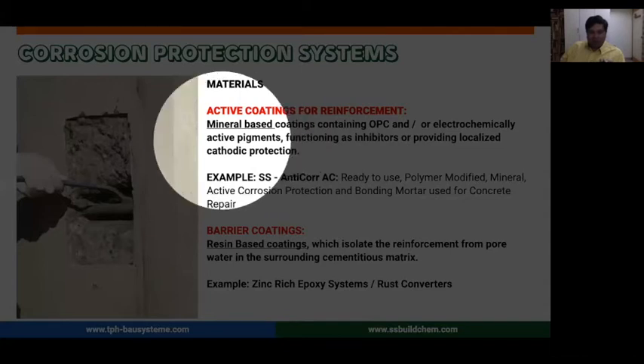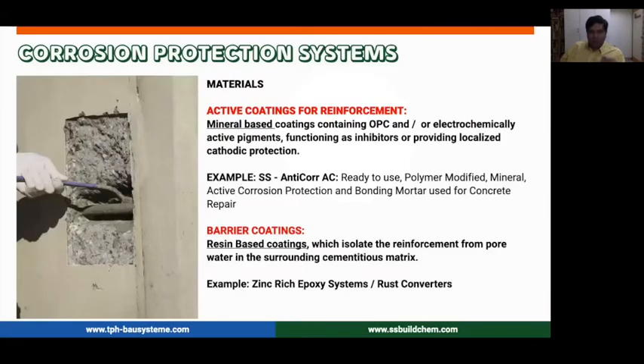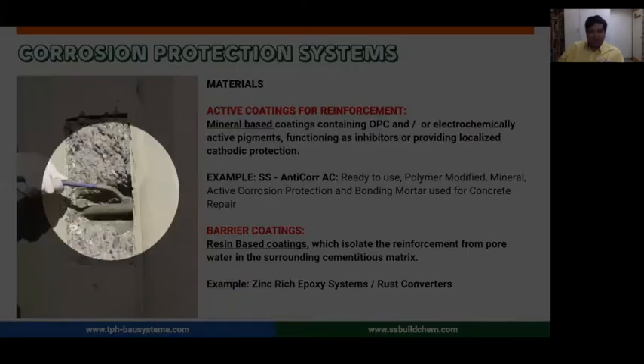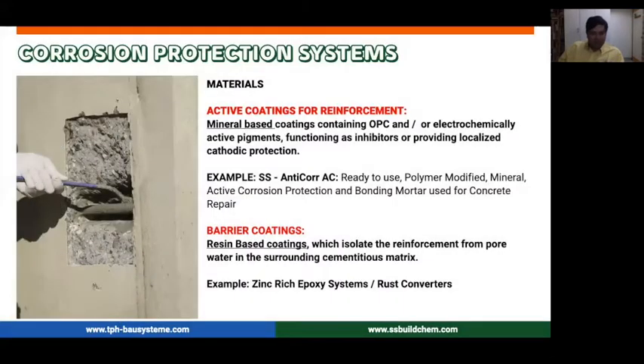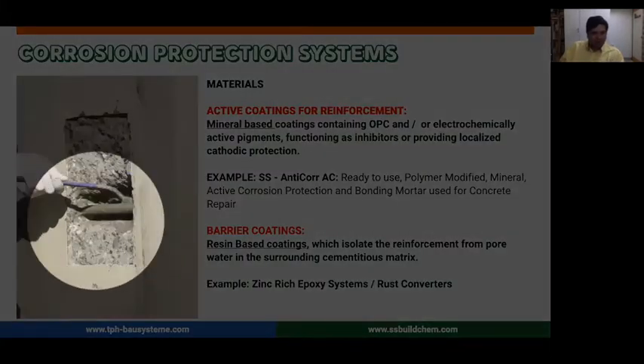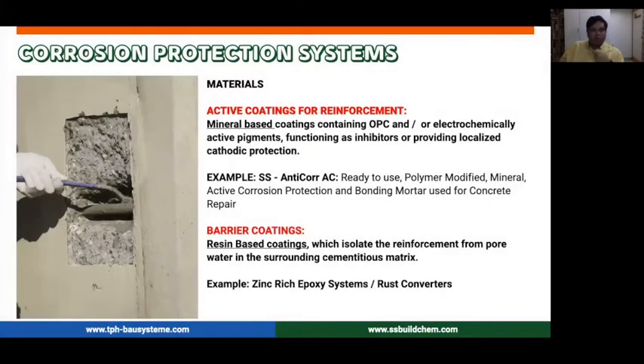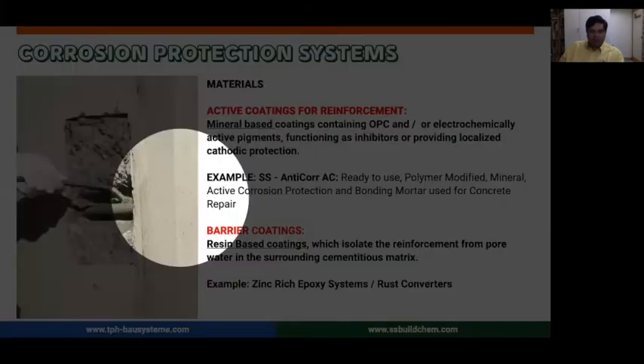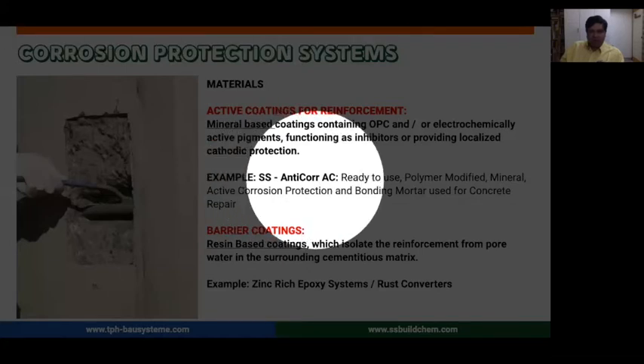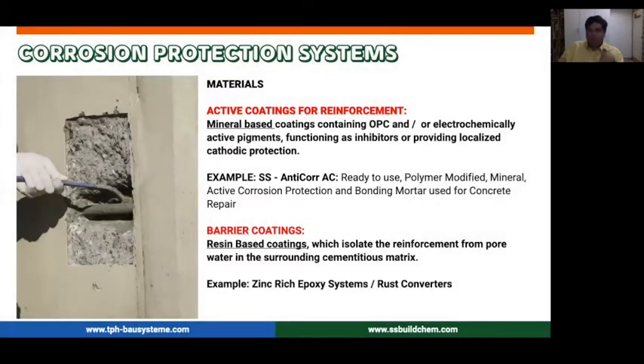So these are mostly mineral-based materials. They contain OPC and other electrochemically active pigments, and these pigments and ingredients act as inhibitors, providing localized cathodic protection. So it looks like this. You just mix a powder with water and apply it onto your prepared steel substrate. For example, the product that we have is called SS - AntiCorr AC. It's very easy to use. It can be used, I would say, 9 times out of 10 for all your concrete repair strategies.